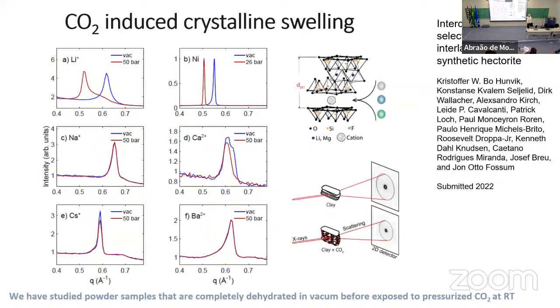So what we observed was that for some interlayer cation situations, there is no shift in the Bragg peak, no swelling when we expose this clay to CO2. So CO2 does not go into the interlayer. But there are two cases, lithium and nickel, where it does. The other ions we have studied here, nothing happens, basically. So they don't capture CO2. So the interlayer cation is important.